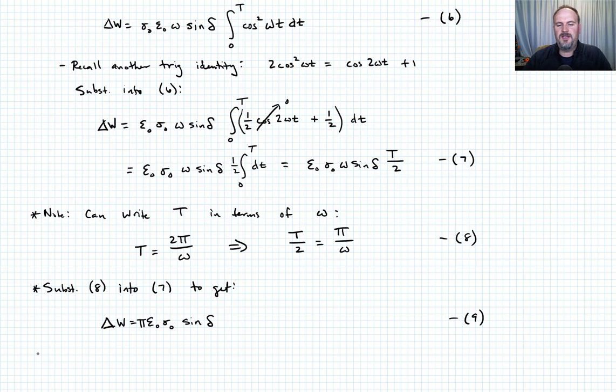Okay, let me also remind you how we defined our loss modulus. So recall one definition for the loss modulus, which was E double prime, which said that E double prime was equal to sigma naught divided by epsilon naught times sine delta. Epsilon naught is the value that we're applying. Sigma naught, remember, had this magnitude of the complex modulus incorporated into it. Okay, so let's call that equation 10.